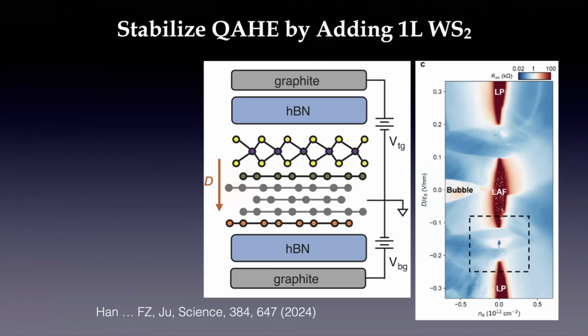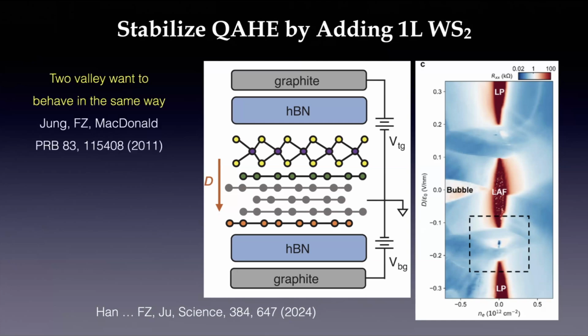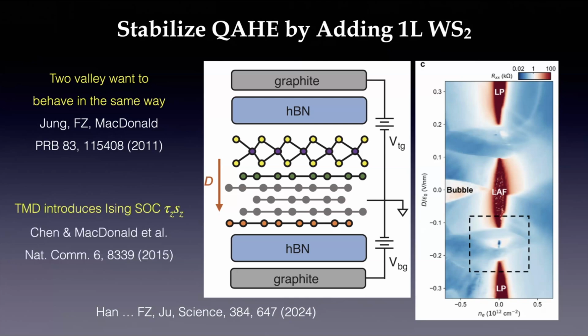The magic of the MIT experiment is that besides the hexagonal boron nitride encapsulated device, they also add a 1-layer TMD to the system. So that TMD can introduce something interesting. At this point I should mention why the ground state is a layer antiferromagnet phase. That is because the valley degeneracy is very hard to be broken by interactions. This has been shown in this beautiful paper. I remember the reviewer asked us whether we were indeed including so many interacting parameters in our system, which is unbelievable. But this TMD can introduce something called Ising spin-orbit coupling, tau_z s_z, which breaks the spin and valley degeneracy of the system. So that is the ingredient added to the experiment.